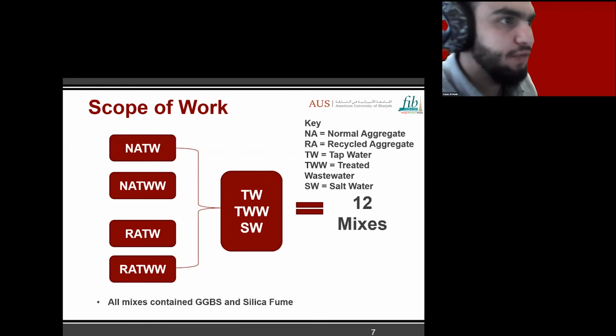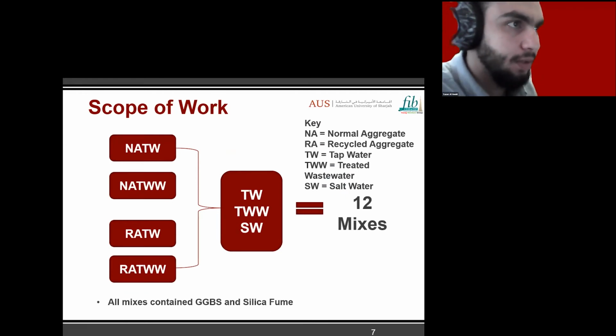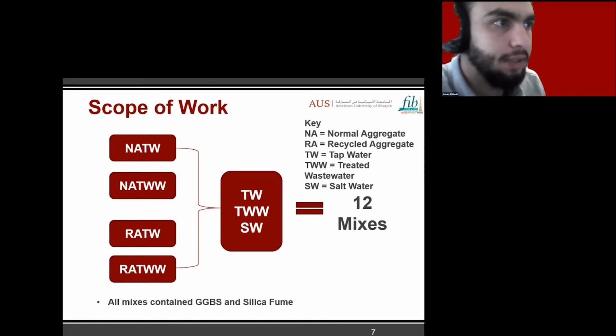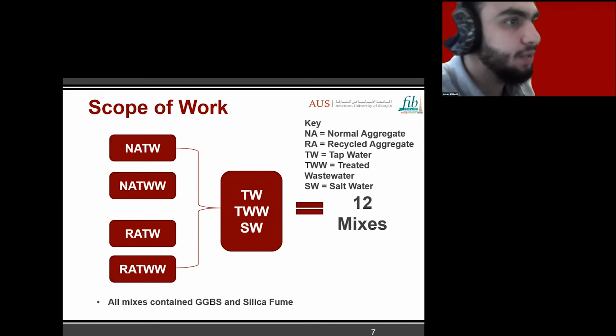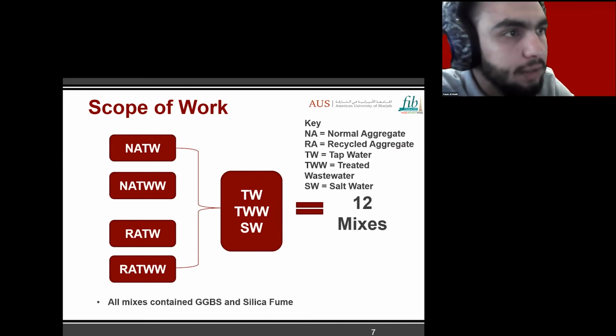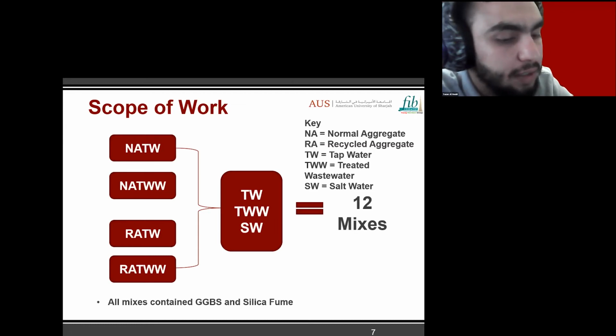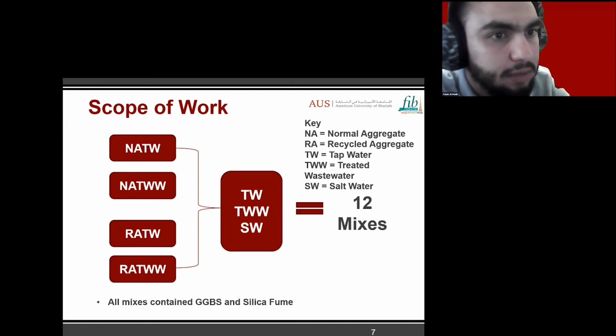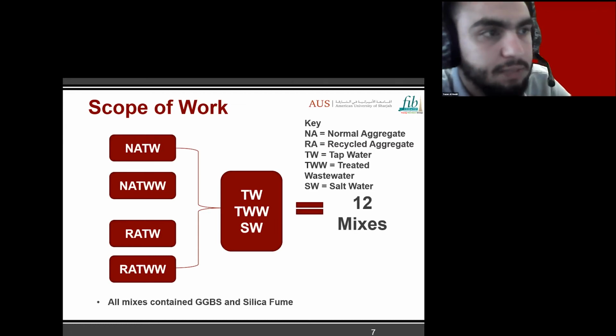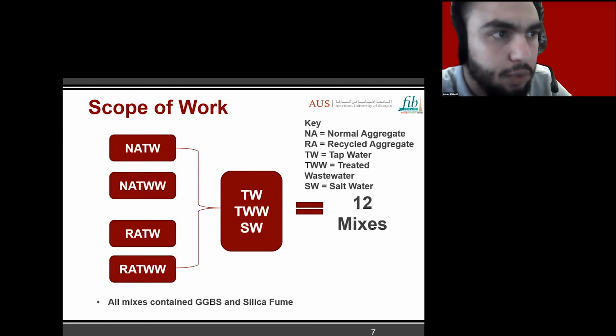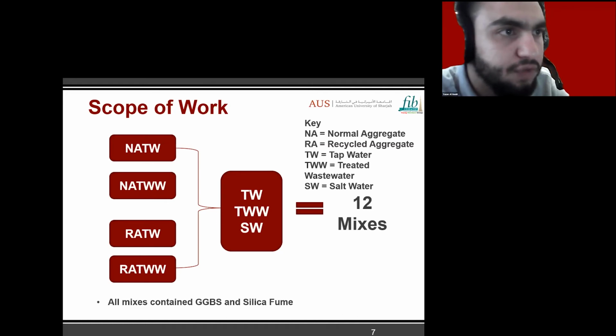So a total of 4 mixes were developed, which are natural aggregate mixed with tap water, natural aggregate mixed with treated wastewater, recycled aggregate mixed with tap water, and recycled aggregate mixed with treated wastewater. Each of these mixes is replicated 3 times for the 3 different exposure conditions, which are tap water, treated wastewater, and salt water, making a total of 12 mixes.